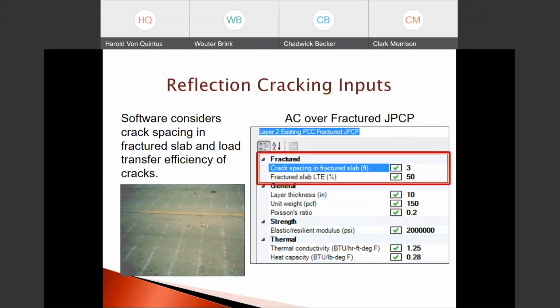The next is the inputs for the AC over fractured jointed plain concrete pavement. There's basically two for characterizing that fractured PCC slab, and that's the crack spacing, which is normally 3 feet. That's the default, but that value can vary from about 2 to 5. And then the load transfer efficiency of those fractures itself. 50% is shown in the screen, and that is the default value. That's the global default value.